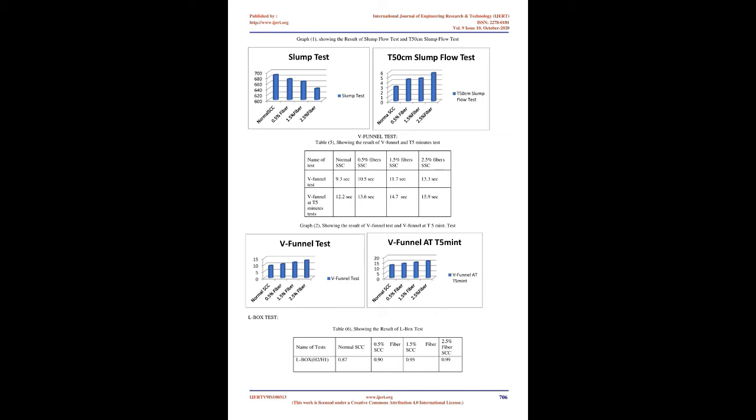In SCC, gravel and crushed rock could be used as coarse aggregate. The maximum size of coarse aggregate is 20 mm, and smaller sizes of aggregate used in SCC are up to 10 mm. Coarse aggregate with a grading similar to that used in conventional concrete may be used. Coarse aggregate of Margalla Hills, with a size of 12 mm, is used in the project.